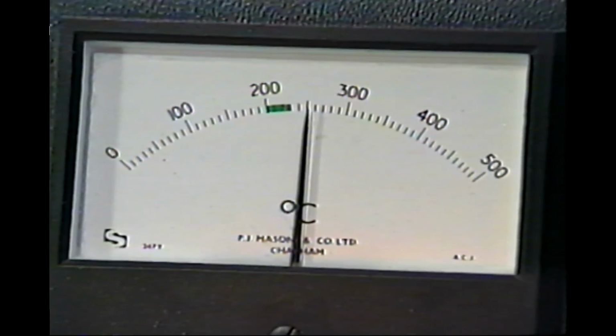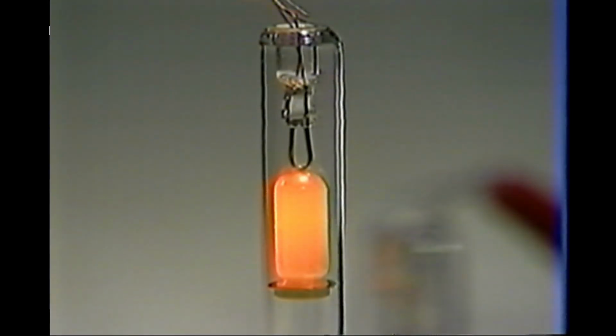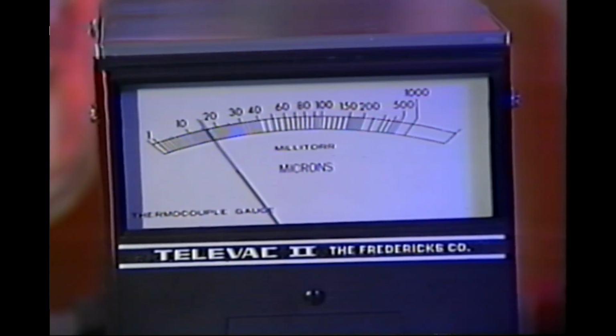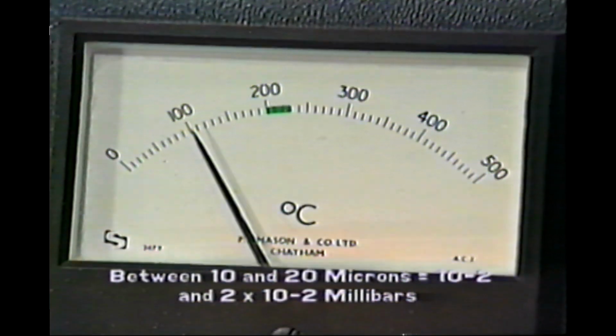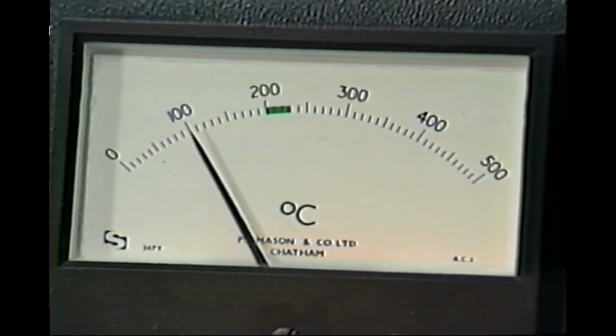The tube temperature must reach 250 degrees centigrade. Switch off the current. Allow the tubes to evacuate to between 10 and 20 microns while the tube temperature falls to approximately 100 degrees centigrade.